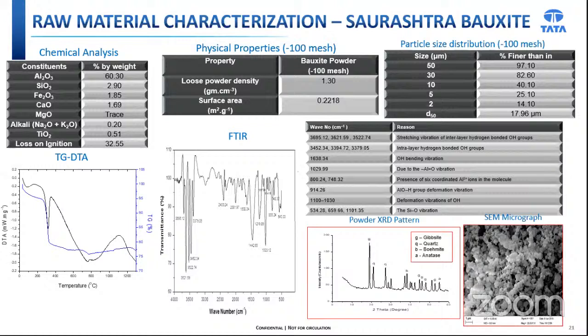The TG-DTA graph of the natural bauxite shows a sharp endothermic peak at 300 degrees centigrade because of the dehydration of hydrated alumina by the expulsion of adsorbed and interlayer water, leading to initial transformation into disordered boehmite phase. The FTIR spectra also reveal that bands at 3695, 3621, and 3522 correspond to stretching vibration of the interlayer hydrogen bonded OH groups, with bands at 3452 and 3379 assigned to the stretching vibration of intra-layer hydrogen bonded OH group.